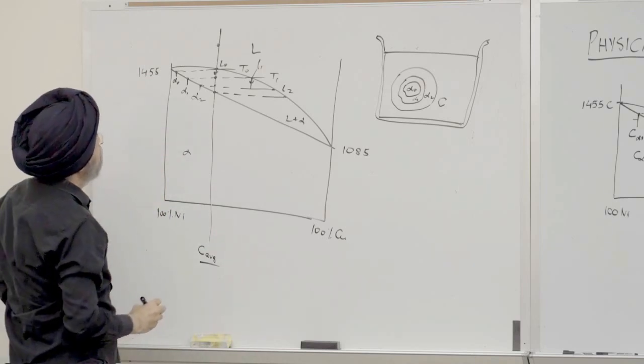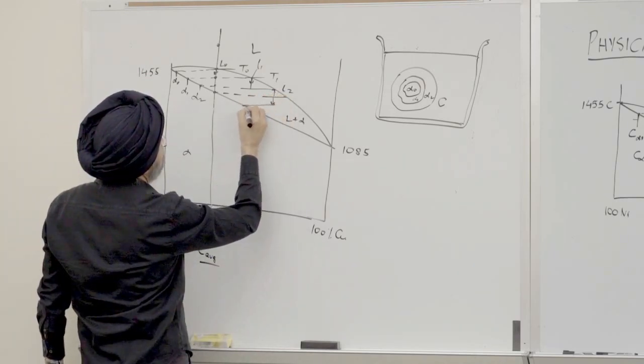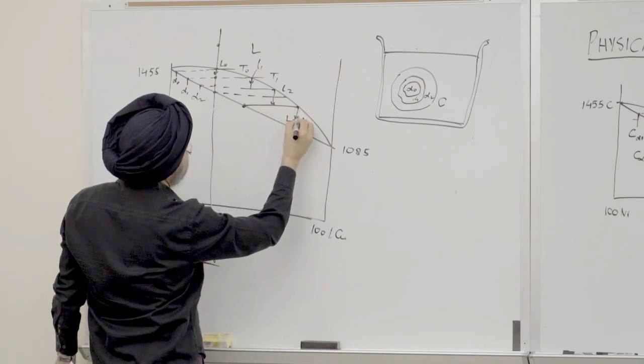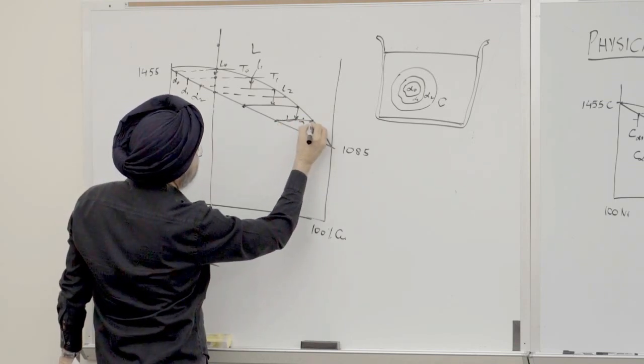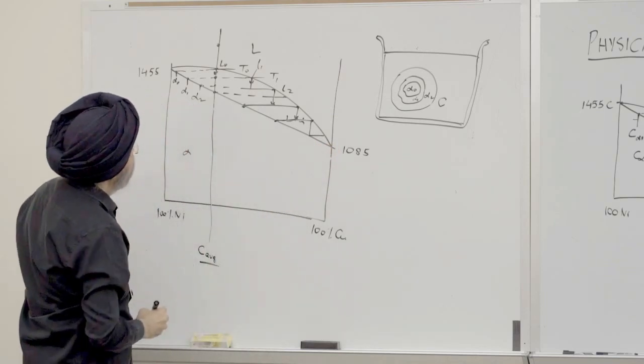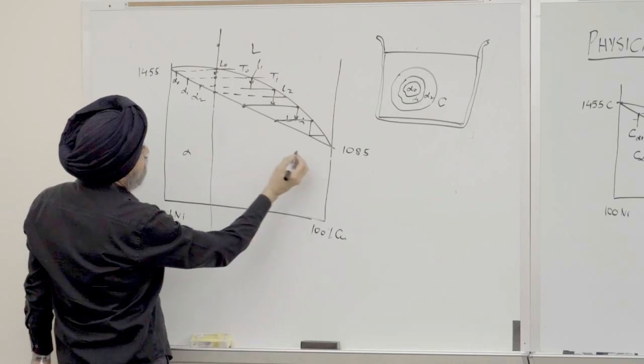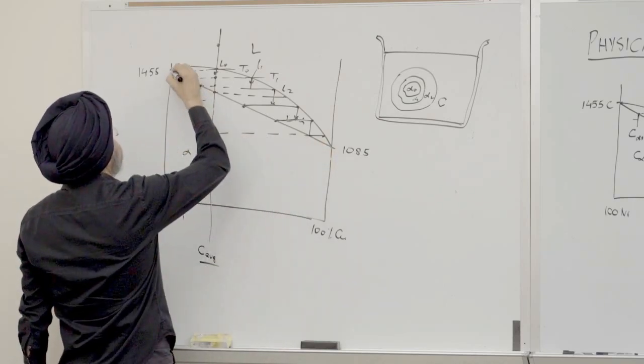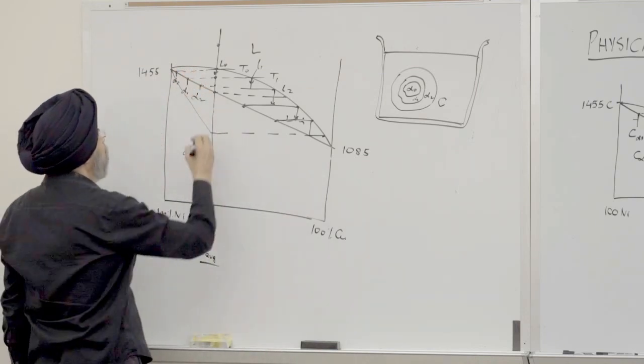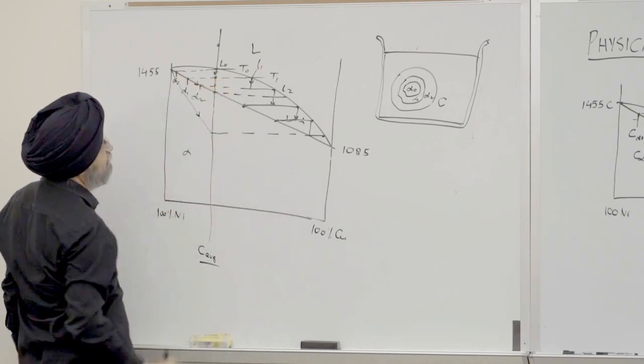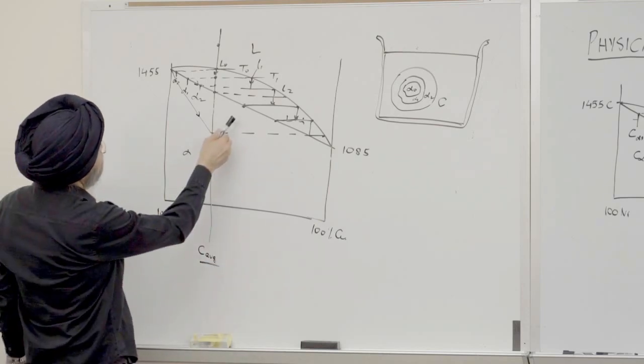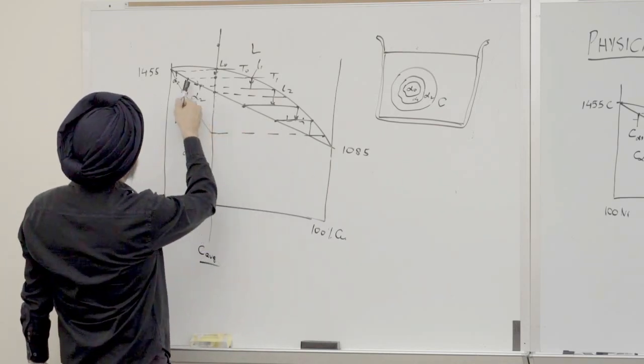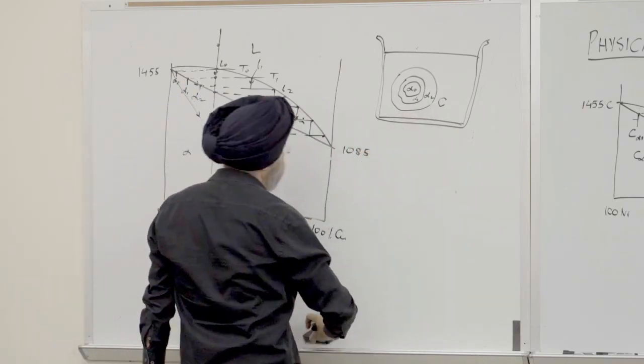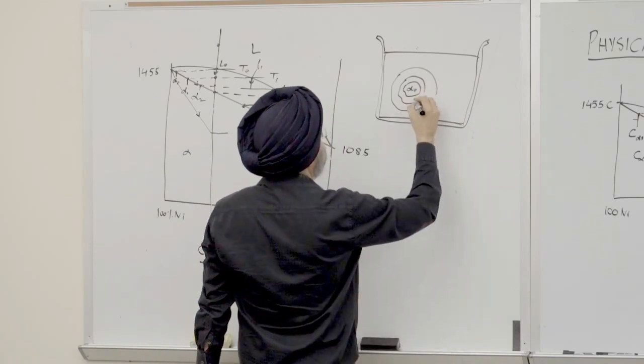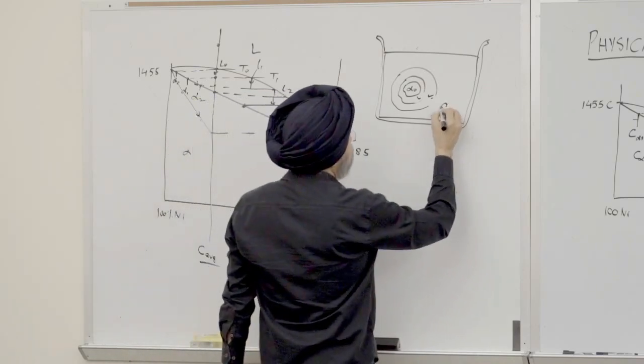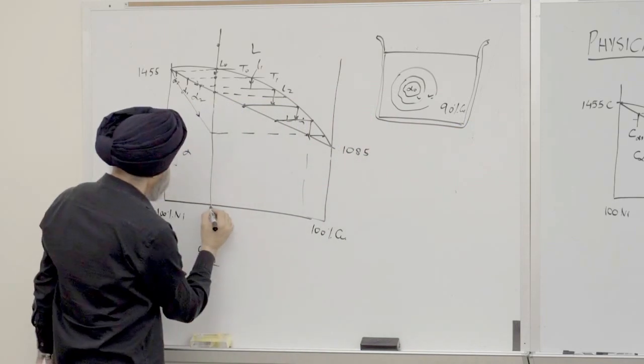So let me just keep going. Then I freeze from here, and this is the composition of the solid, and this is the composition of liquid, and the liquid, we come here, and this is the composition of solid, that's the composition of liquid, and so on. So let's say everything solidifies over here, this curve follows like this. So instead of following this line, we're following that line. Notice that the solid that is freezing later on, the composition of the solid keeps on increasing. So it's not like I've drawn over here. These values are much higher. And this value is probably like 90% copper, even though the average was, let's say, 30%,